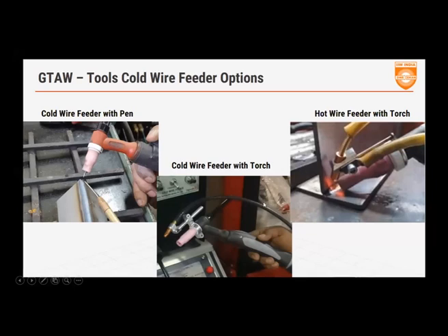If the welder wanted to use a cold wire feeder, using a torch with an inbuilt feeding range, the liner could be mounted on top of the torch here, as you can see. You can adjust the height and the angle at which you would want to feed the wire. These would be very good for longer straight seams, but if you had fillet joints or narrow grooves, this kind of a setup would be much better.